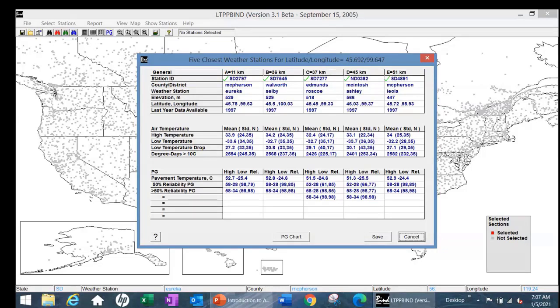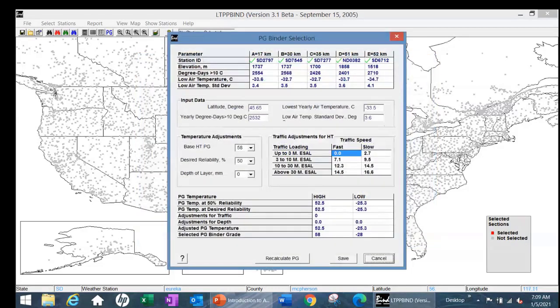You can also get specific. We talked about rate of loading. The other thing, cold temperature effects drop with depth into the pavement, right? If I'm doing 2 or 3 2-inch lifts, I don't need the minus 34 in the bottom 2 lifts, because the lower I go in that pavement structure, the closer I get to what temperature? 0 degrees centigrade, right? Frost line, 32 degrees Fahrenheit.